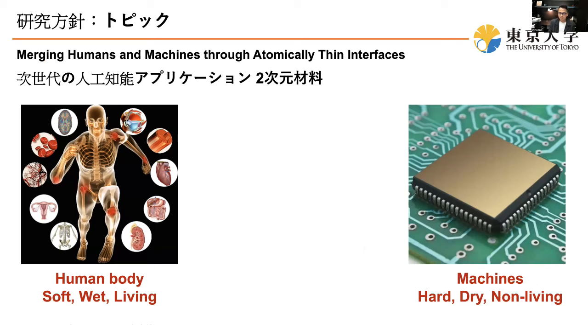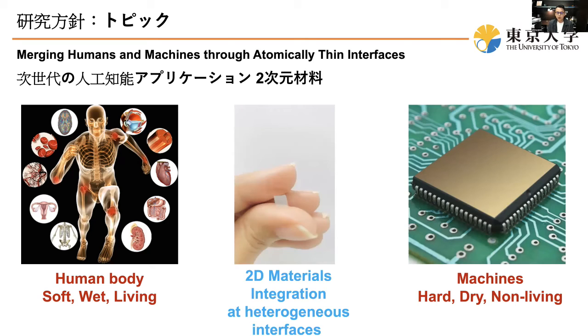But machines, they are hard, they are dry, and they are non-living. So our goal is that by utilizing these atomically thin materials as the active interfaces, we take these materials and stack them together. Even though you stack 10 layers, they're probably only less than 20 nanometers thick. So you have the functionality while keeping the flexibility for integration. So this is the recent direction that we are aiming for.